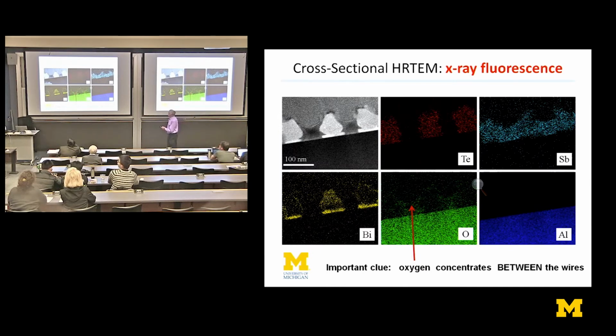It's telling us that the oxygen, even though the tellurium is concentrated within the wires, the oxygen, first of all, there wasn't any oxygen originally, it was just antimony telluride. Now we've got oxygen in there, and it's occupying sites between the wires. In other words, in these valleys between the wires, there's a substantial amount of oxygen. And the aluminum here is from the substrate, obviously. So this tells us there's something chemical going on as well as physical.